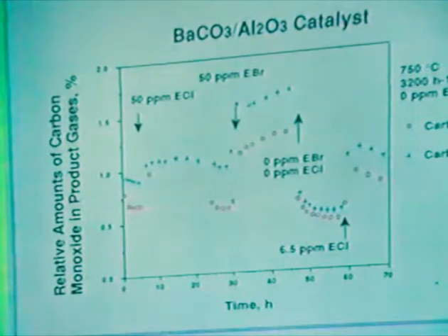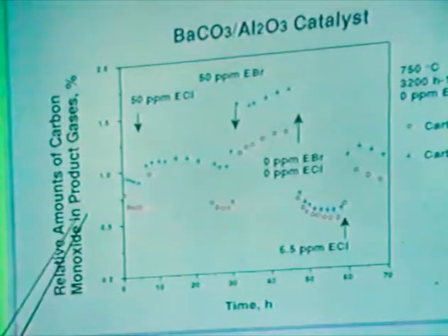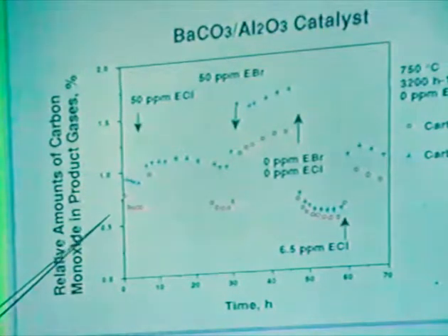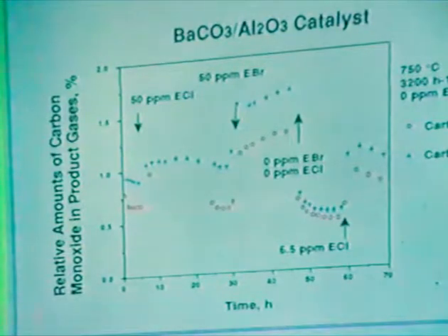And if you run control studies, you see that methane conversion increases by less than 1% if you just have a void space without a catalyst. That's not a problem. So what you see is CO, which is the blue pluses here. In each set of a variety of conditions, CO is produced at a higher rate in the reactor that has the void space after the catalyst, meaning there is increased gas phase contribution to this reaction, under all conditions. And we do know from combustion chemistry that CO is the primary product of the oxidation of alkanes.